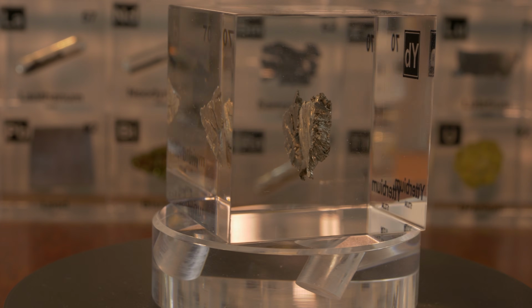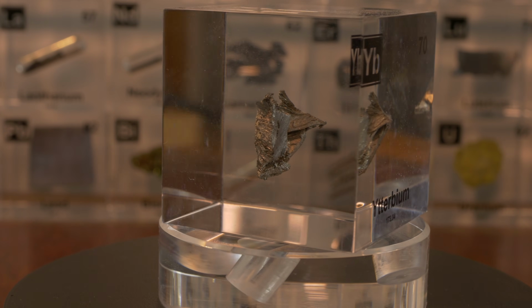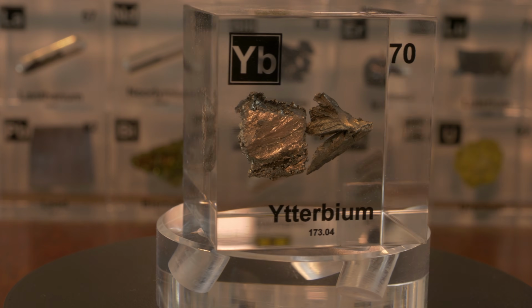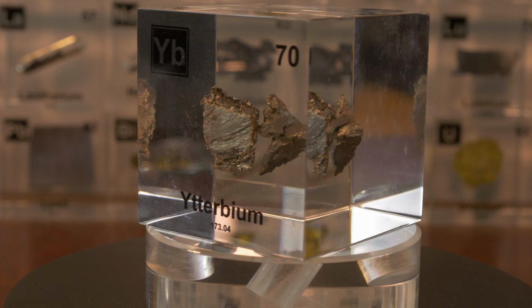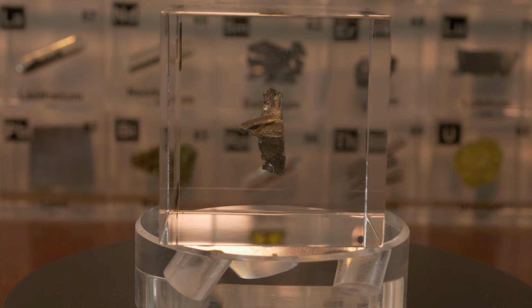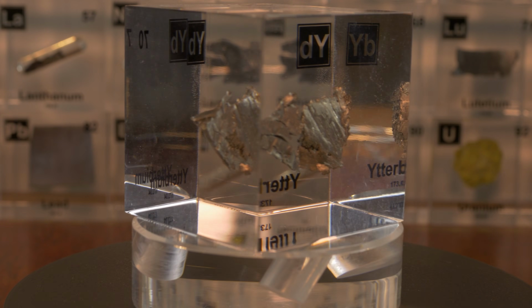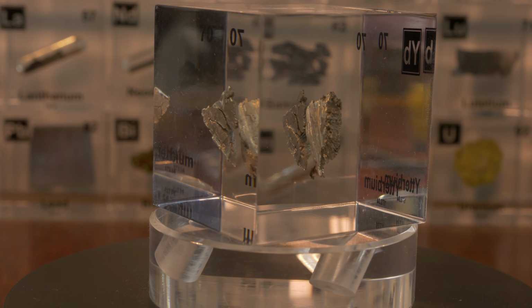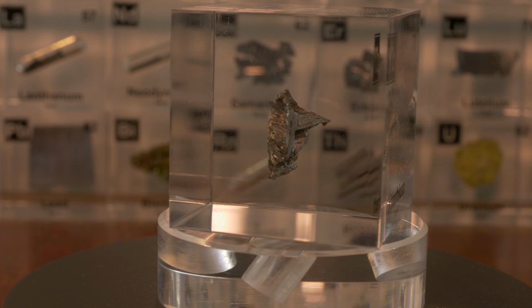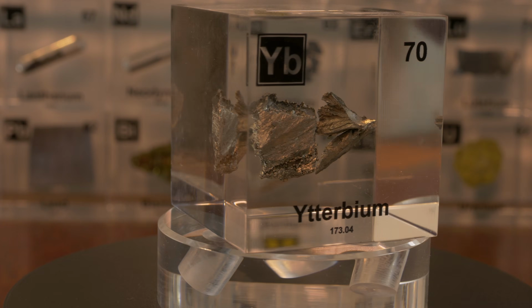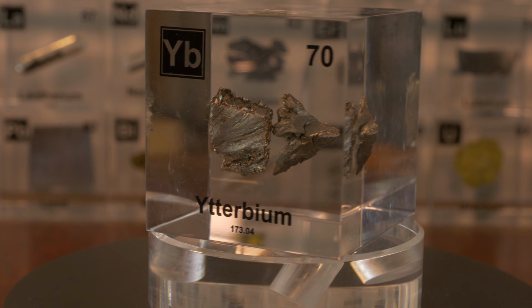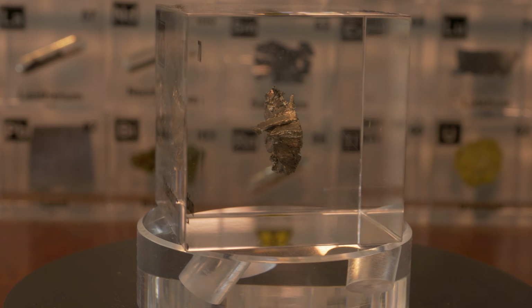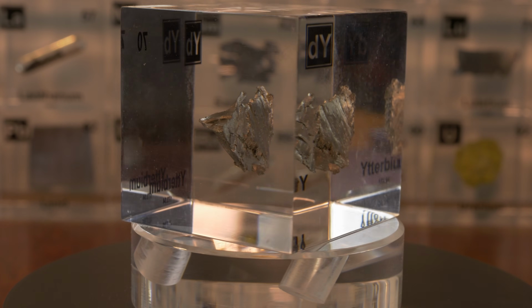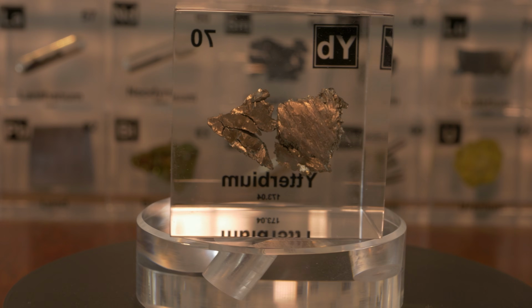Well, it has a relatively simple energy level scheme with a small quantum defect. This means the difference in energy between the pump light and the laser output is smaller, which translates to less wasted energy and heat, and more efficient conversion of pump light to laser light. Ytterbium lasers can achieve high efficiencies. Over 60% of the pump energy can turn into laser energy, which is huge for lasers. They also tend to have long operational lifetimes, and they can be pumped by reliable laser diodes. Additionally, Ytterbium-doped materials can often be run at high doping levels and high powers without some of the issues that other dopants have.